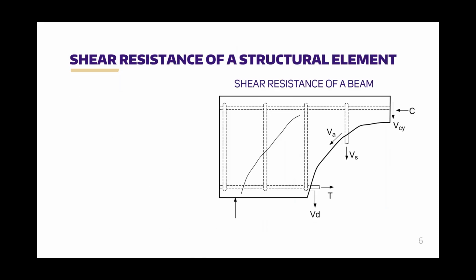So going back to the shear resistance of a beam, we know there's contributions from a number of different sources. And really what we're looking at in this case is there a contribution from those fibers crossing the crack? And can we quantify that and codify that? And like I said before, beams have been the typical way we've done this. Unfortunately, that involves both flexure and shear, and so there is that coupling that we have to deal with.